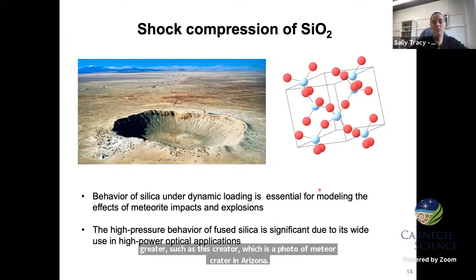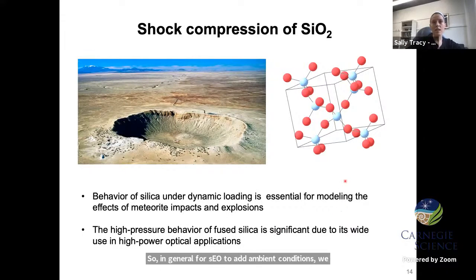So in general, for SiO2, at ambient conditions, we know that it adopts a crystal structure where each silicon atom is coordinated by 4 oxygen ions in a tetrahedral coordination. But what we expect to happen in general at high pressure is that we'd adopt a denser structure with likely 6-fold coordination. So here we'd expect each silicon to have 6 oxygen neighbors, and this type of structure is likely to be stabilized. However, the details of the crystal structure that forms during shock loading were until recently unresolved and a topic of some debate.